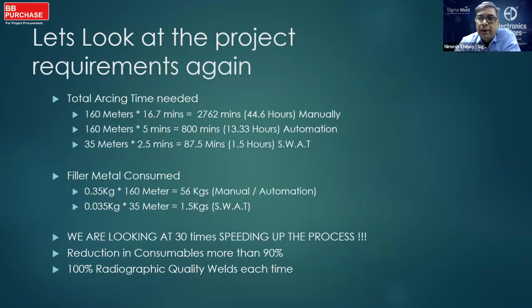Let's look at that number again. The arcing time required for manual welding was 44.6 hours. The arcing time required for automated welding was 13.33 hours. The arcing time required now is 1.5 hours. This is at least 30 times the speed that you could have improved. Filler metal required was about 0.35 kgs, that is 56 kgs in manual or automation. In SWAT, you would only need about 1.5 kgs to do this job. So you can imagine the kind of saving out there as well.